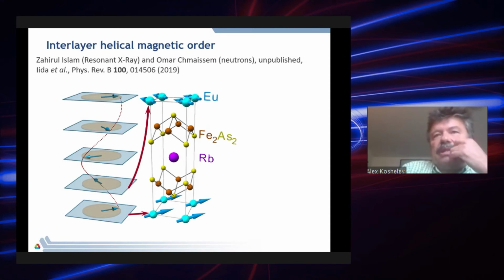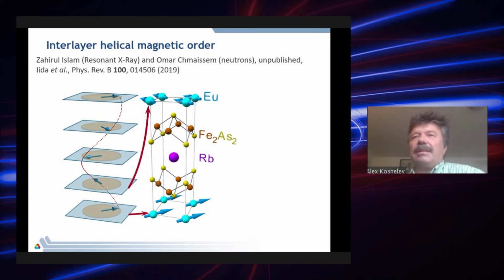Later it was discovered that the interlayer magnetic structure is kind of peculiar. It has a helical shape. I myself learned this structure from my colleague Zahirul Islam, who performed resonant X-ray measurements, and later our colleague performed neutron scattering. Unfortunately, these data are still unpublished, and the main reason was that a Japanese group published a paper when they had already obtained this structure by neutron scattering.